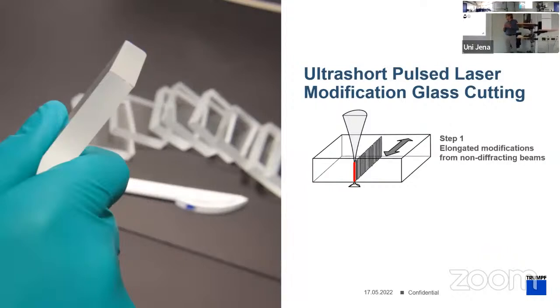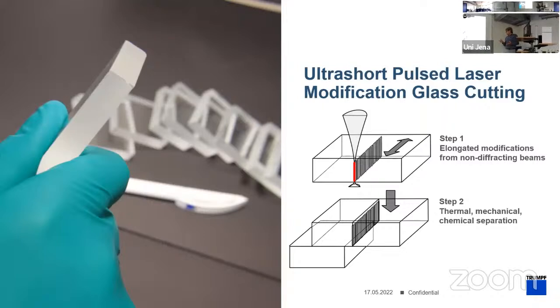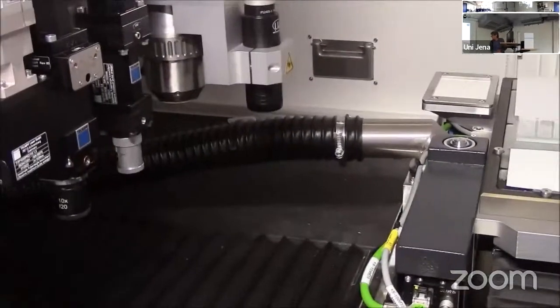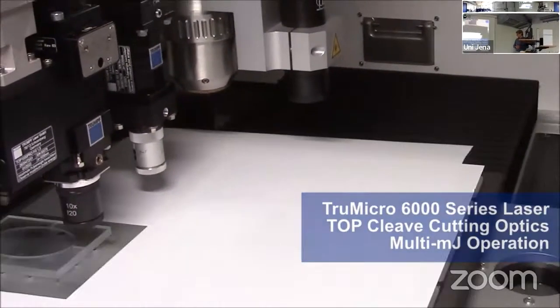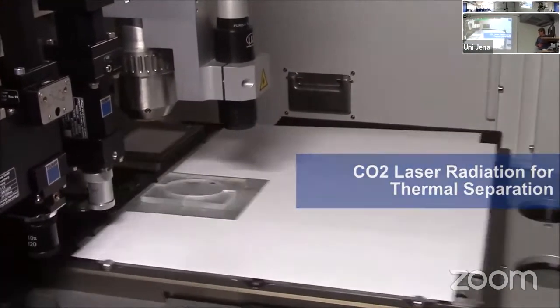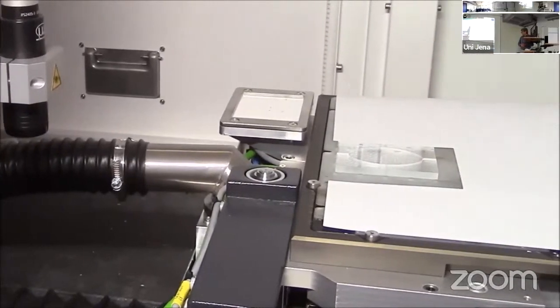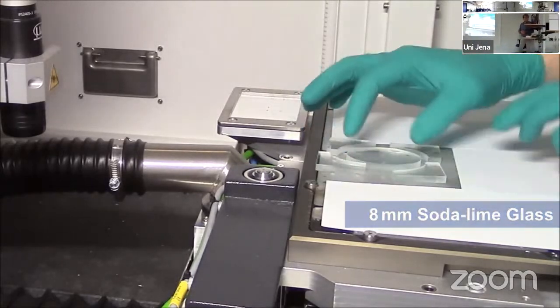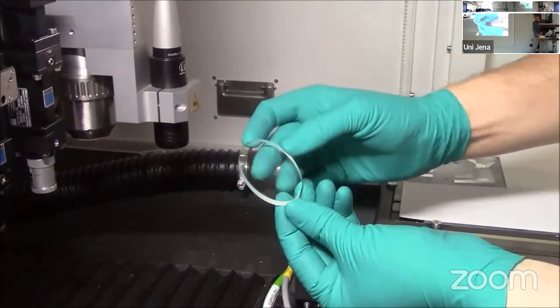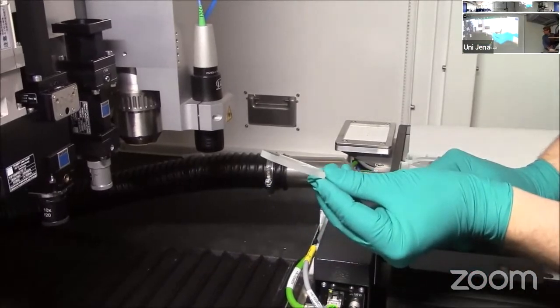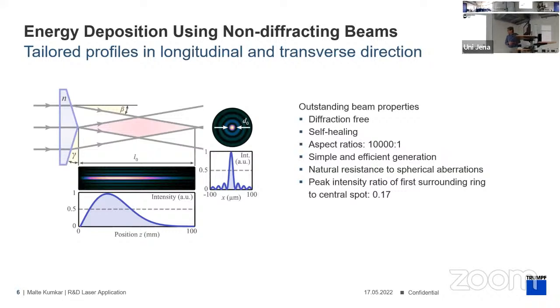So first I want to go on with the elongated modifications for non-diffracting beams. This is very attractive because they do not change the intensity profile during propagation. And it's normally a two-step process. So first inscribing, and afterwards use mechanical or thermomechanical stress, or maybe chemical separation. So just to give an impression how this works. So this is inscribing. So 6 millimeters, then CO2 laser for crack propagation. And then it's going to be easy to separate. Yeah, and it's possible to generate complex shapes.